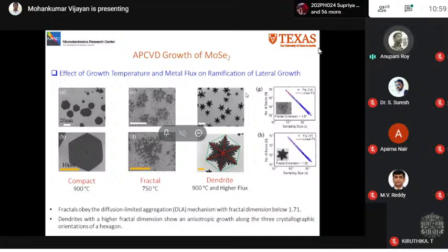And you can see from the fractal dimension calculated in the case of the dendritic domain, shown in figure H, that the fractal dimension is a little bit higher. It is about 1.8 to 1.82, and that indicates that at 900 degrees C with higher metal flux, the growth is not random anymore.